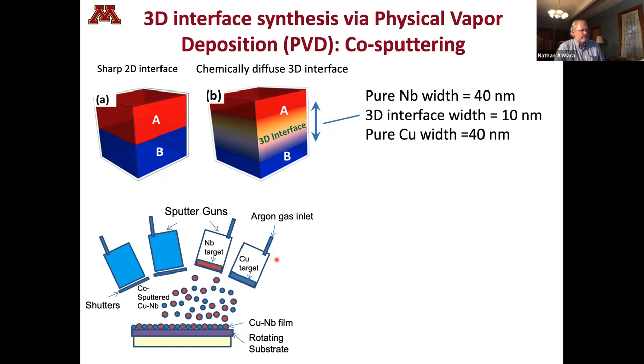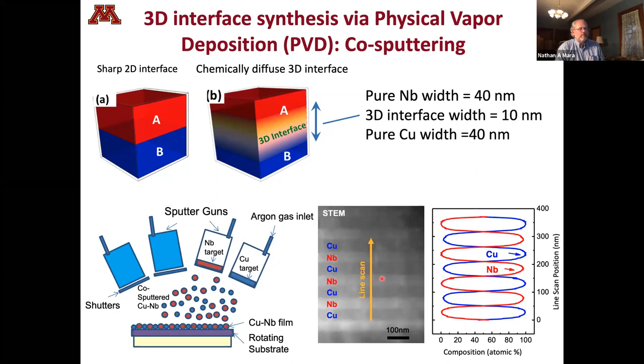So we'll look at a case where we've got pure copper of about a 40 nanometer layer thickness and our interface width is about 10 nanometers, and then you have more pure niobium on the top, 10 nanometers of 3D interface, and then 40 nanometers again of a pure phase and so forth. When you grow these and you stick them in the TEM, this is what they look like. You can do an EDS scan across them like this. And what you find is that you get these nice smooth profiles indicative of a smooth compositional gradient.